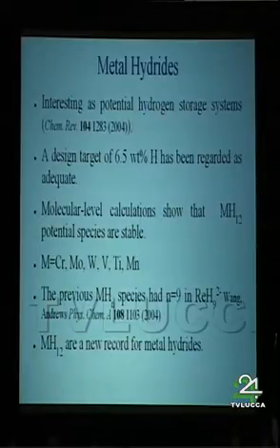So we have invented this new series of molecules with general formula MH12, where M is a group 6 metal: chromium, molybdenum, tungsten. And if you consider the ionic species, the idea works also with vanadium, titanium, manganese. And this represents a record for metal hydrides, in the sense that in the literature there were known species with up to 9 hydrogen atoms, ReH9 2-. So having 12 hydrogen atoms is a record in this sense.